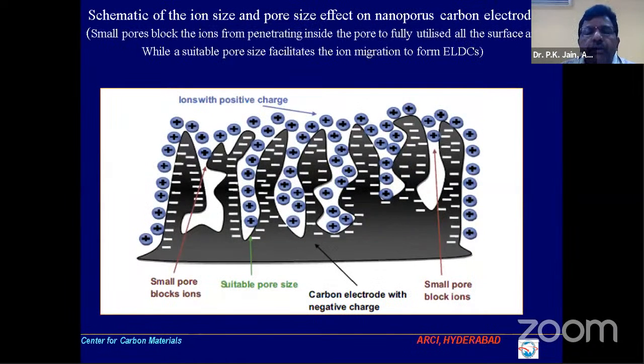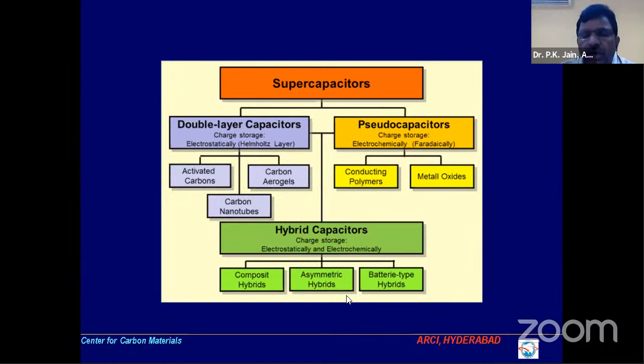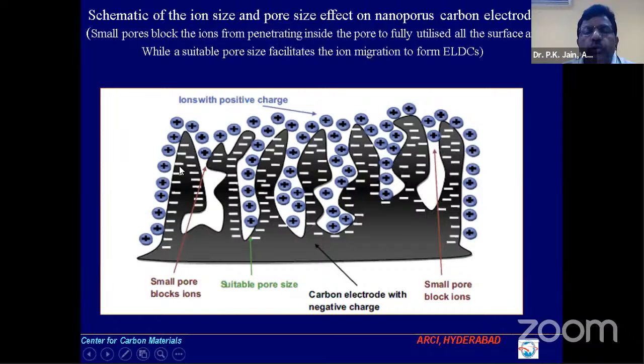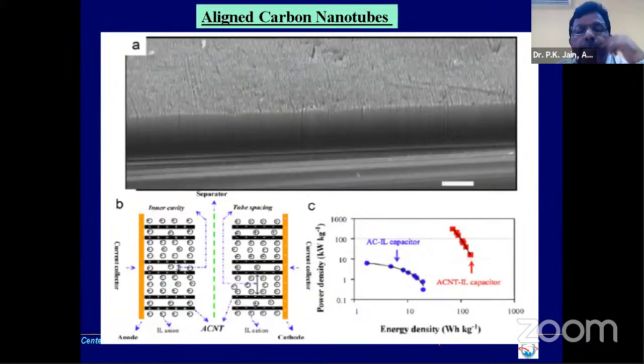But the important point here is that all these things involve a surface charge transfer. So you require a very high surface area material as an electrode. This high surface area electrode can be activated carbon or different types of nanocarbon. People all over the world are doing research on different types of surface processing so that the specific surface area can increase, and then finally the charge discharge and the charge density can be controlled. Aligned carbon nanotubes were also one of the possible materials, because the charge can be adsorbed onto the different surfaces of the nanotubes.